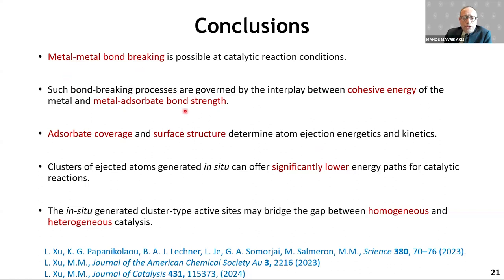Bond breaking processes are governed by a delicate balance between the cohesive energy of the metal and the strength of the metal-adsorbate bond. Clearly, we saw that adsorbate coverage, which connects with pressure, reactive gases, and surface structure, kinks versus terraces versus step edges, determine the ejection energetics and kinetics.